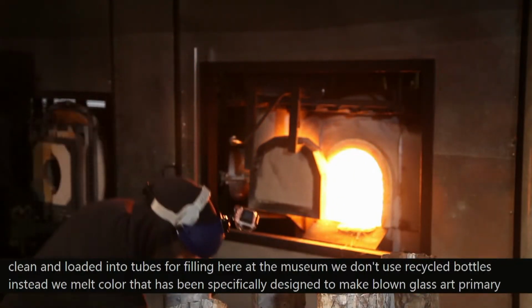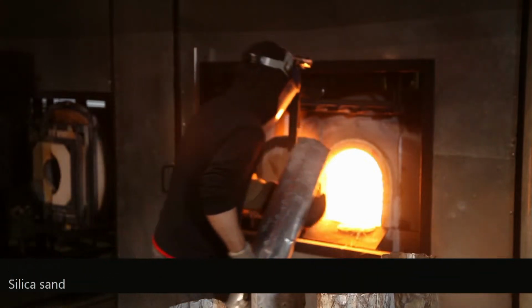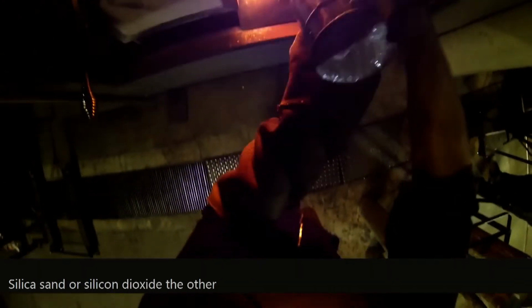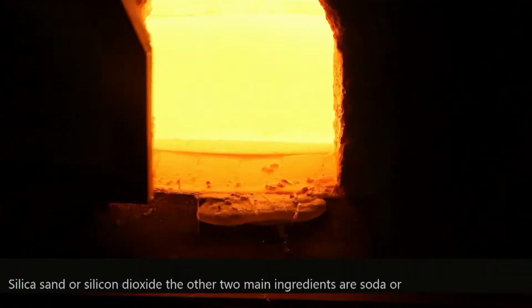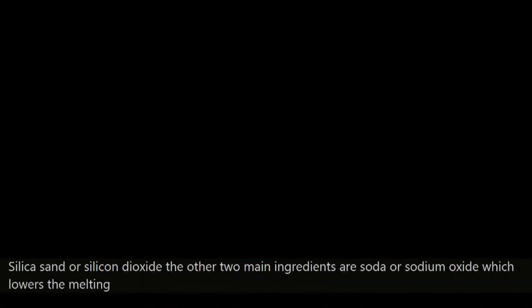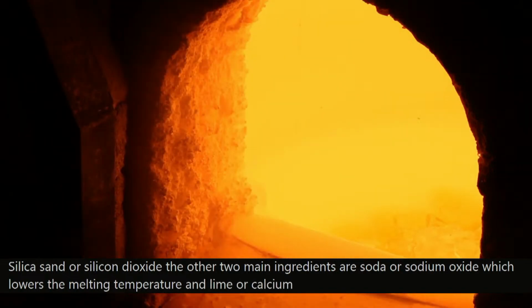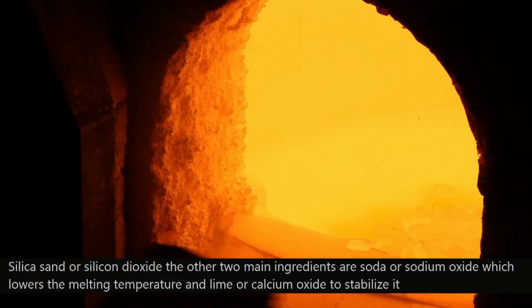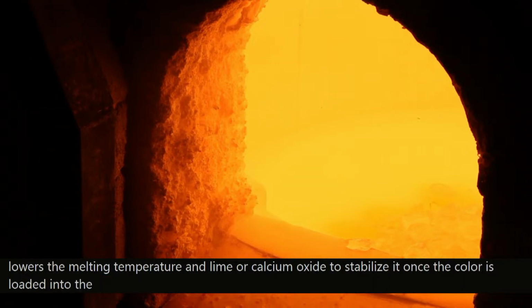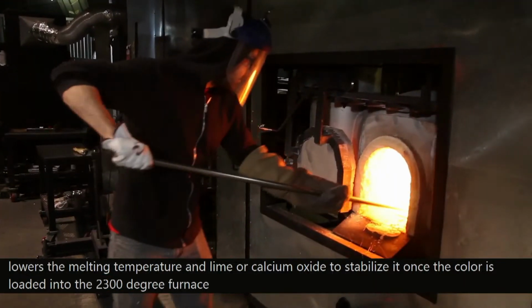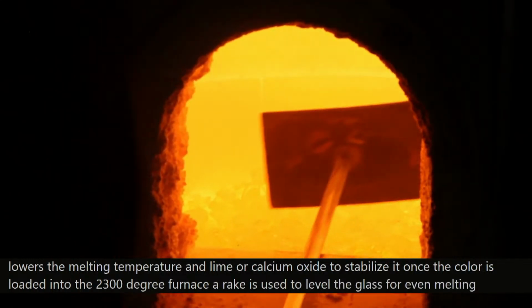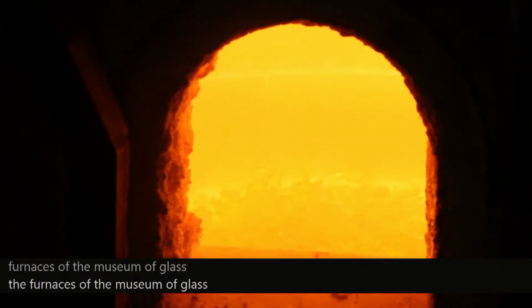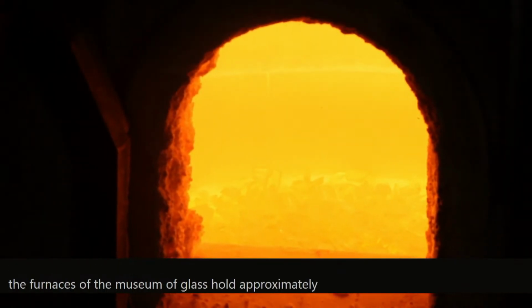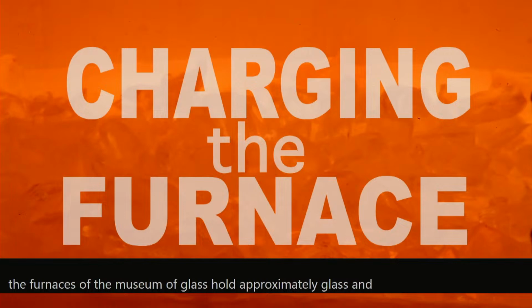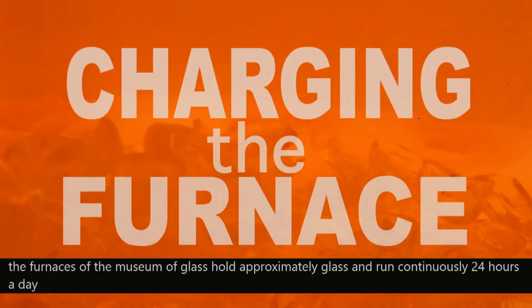The primary ingredient in glass is silica sand, or silicon dioxide. The other two main ingredients are soda, or sodium oxide, which lowers the melting temperature, and lime, or calcium oxide, to stabilize it. Once the color is loaded into the 2300-degree furnace, a rake is used to level the glass for even melting. The furnaces at the Museum of Glass hold approximately 1,000 pounds of clear molten glass and run continuously 24 hours a day, 7 days a week.